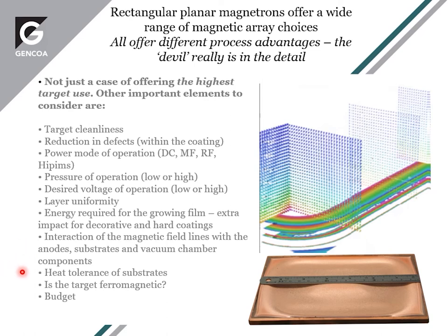Sometimes substrates are not very tolerant to heat, so you have to be careful that plasma released from the magnetrons doesn't enhance substrate heating. We also have practical limitations such as ferromagnetic materials — nickel and iron — where the magnetic field from the magnetron gets absorbed in the target, making projection of the field through the target more difficult. And obviously budget is very important: we have various sophisticated magnetic designs but they're not always appropriate for every situation.